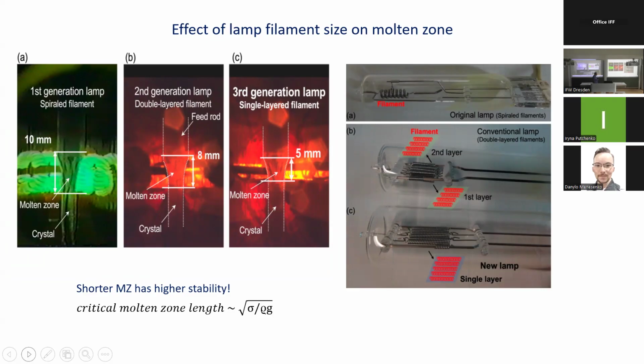And usually a shorter molten zone has always higher stability. Also, there is a so-called critical molten zone length, and any molten zone that has a length above this critical value is completely unstable. So that's why we prefer shorter zones.